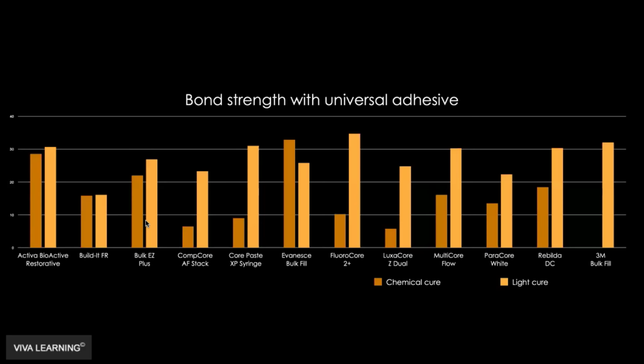So that means that, let's say you've got this big deep prep, and you're like, oh, because I've got a big deep prep, I'm going to use this dual cure buildup material or this dual cure restorative material and squirt it in there. I will cure it from the top, but I know it's really deep, so I'm just hoping the stuff down on the bottom layer cures from a chemical cure mechanism, and that's the relief I'm getting by using a dual cure restorative material. The problem is, if that dual cure restorative material is not compatible with your bonding agent, you won't get a good bond. So that's what I'm saying.